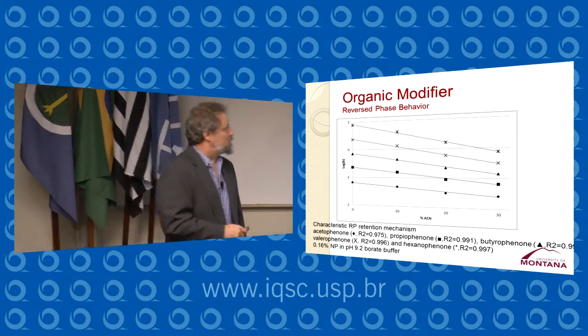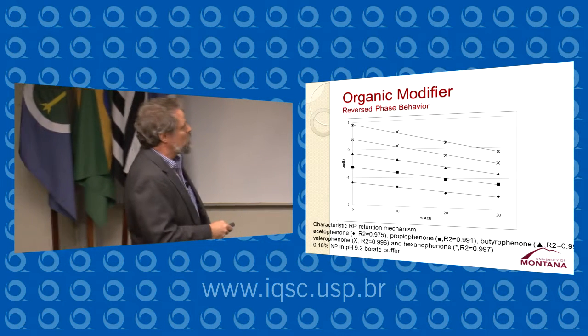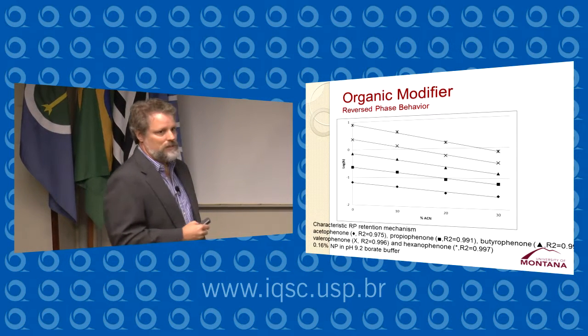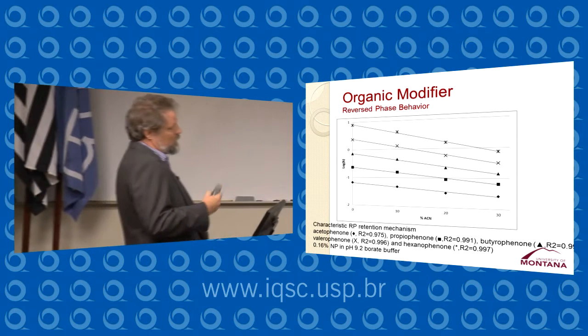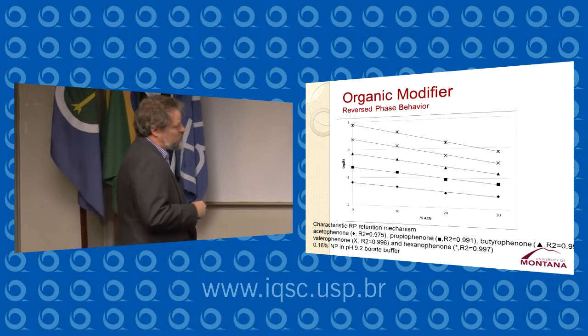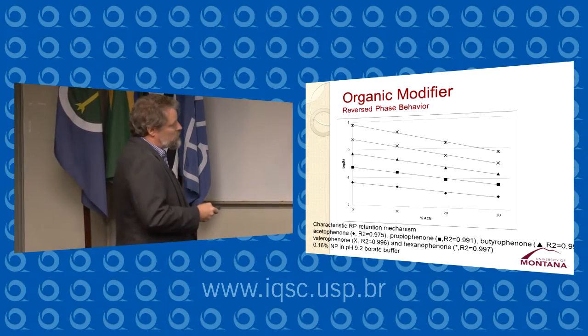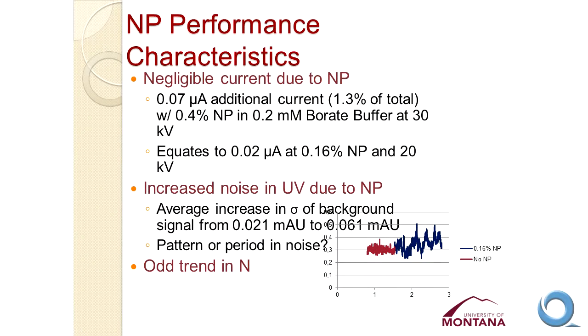So the performance characteristics: almost no current is carried by these nanoparticles. I'll show you what that means for us in just a second. We do see some increased noise in UV detection, and you can see that here. This is without nanoparticles, this is with nanoparticles. So there is a substantial increase in the noise, but still we're able to get reasonable detection. And we did observe this odd trend where some of those peaks are fronting a little bit, but we still don't really understand it.